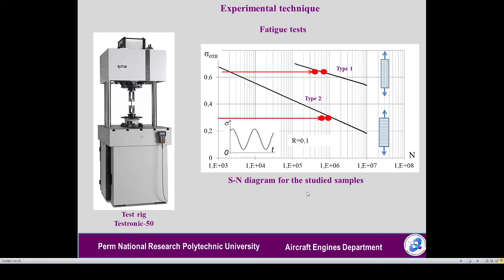The load amplitude was chosen so that the lifetime N of the sample was about 1 million cycles. For this purpose, the fatigue curves obtained in advance were used. The relative stress amplitude was 0.64 for the first type of samples and 0.3 for the second type.